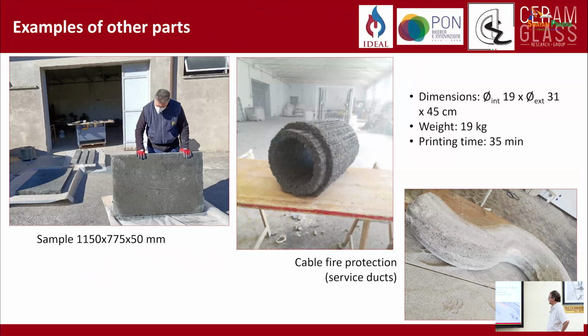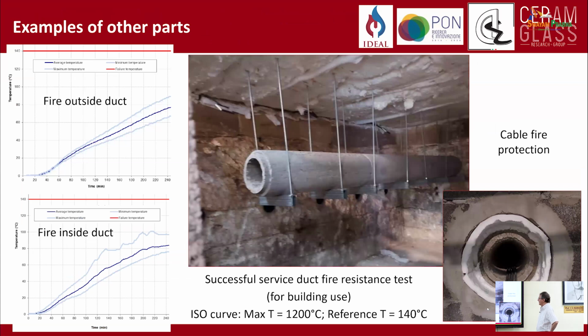You can see here something that was done at the company. So for cable fire protection, service ducts, we can make large parts and parts with different shapes as well. This is a test for a service duct, the fire resistant test, and the limit for the temperature was not crossed. So this again is a successful test showing that we were able to achieve the desired results for this project.